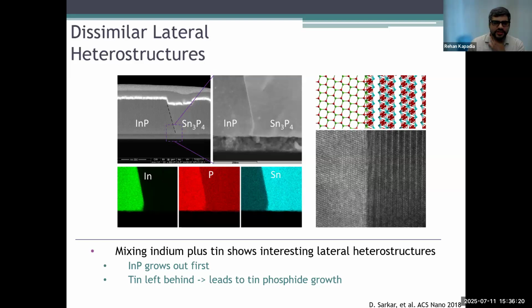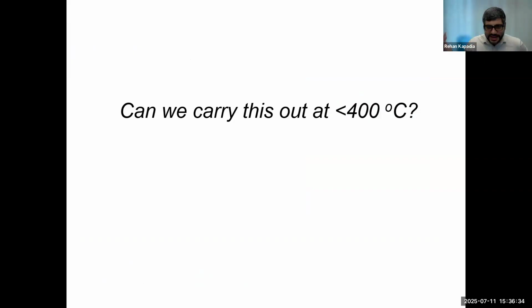But at this time, one of the questions that we had, so this was published in 2018, and this was work done in 2017, and about that time, everyone was starting to think about, okay, what about back end of the line integration? There's many rules for back end of the line integration, but there's really one rule, and that's you have to maintain your thermal budget. The exact thermal budget will vary from CMOS technology to CMOS technology, but in general, the rule of thumb is we need to be below 400 degrees C, and if we're below 400 degrees C, we're probably not going to cause any significant damage to, say, the gate stack or the silicides for the contacts. We're not going to do any kind of irreparable damage. That's the typical rule of thumb.